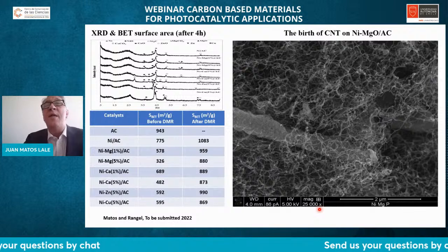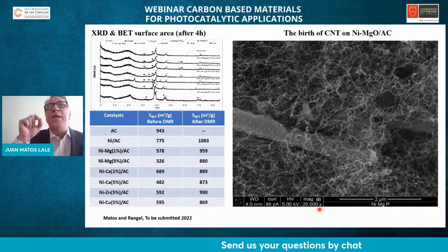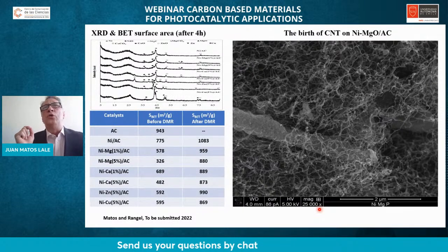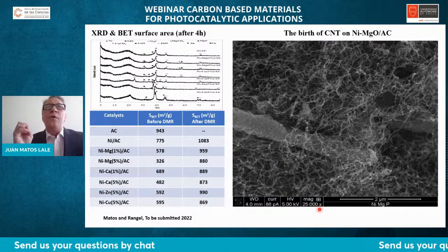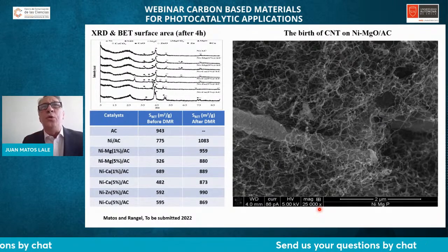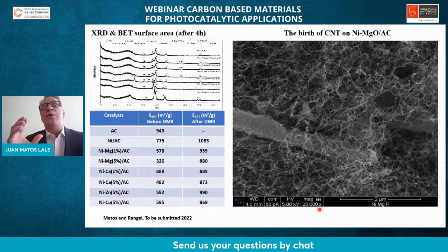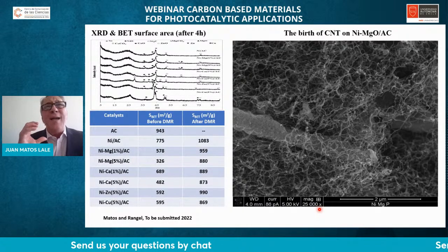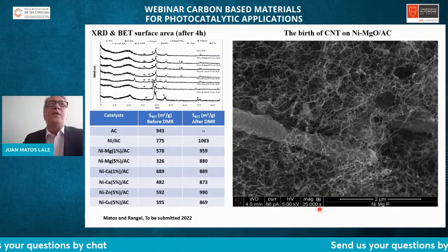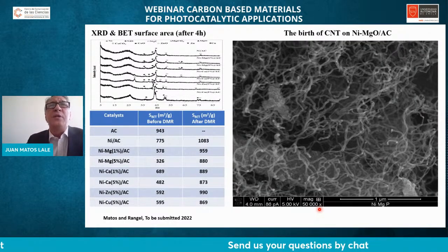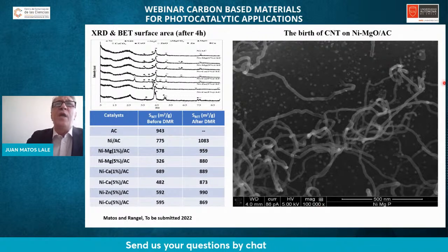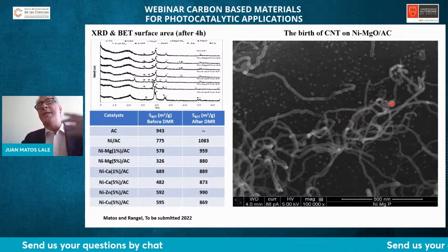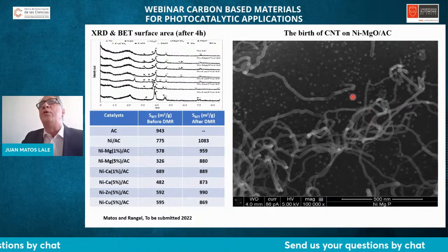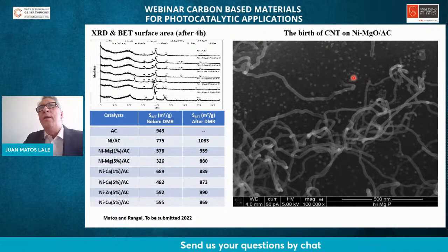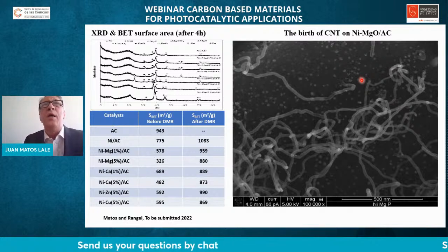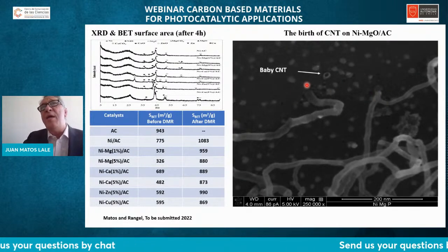At the same time, we have been able to control the surface functional groups and the pore size distribution of nanoporous carbon materials to induce the formation of very highly ordered carbon nanotubes of very equal diameter. For instance, we can see in this example the increase in the quantity of carbon deposits in the shape of multi-walled carbon nanotubes. You can see here this point that I noticed with the laser pointer, and this is what we are talking about, a baby carbon nanotube.